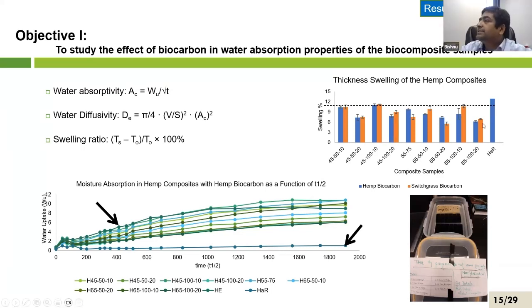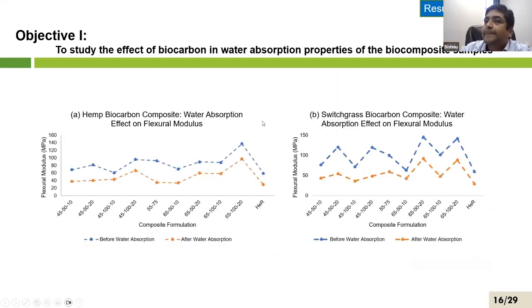Yeah, so here we can see that with 20%, definitely it provides better resistance to moisture uptake. So this is the flexural modulus before water absorption and after water absorption.